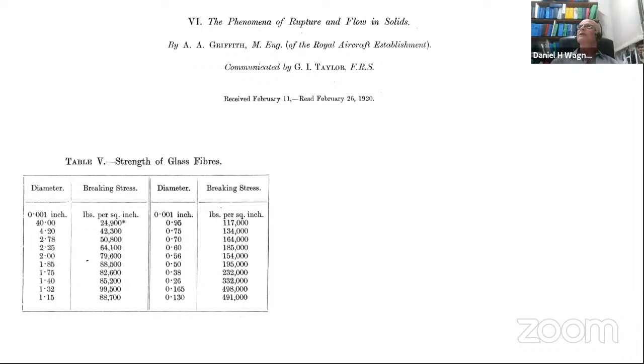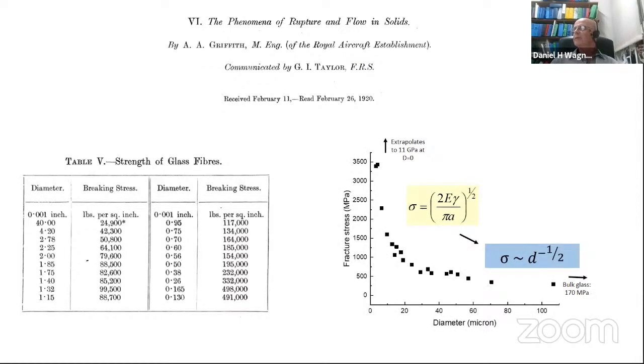And this is from the original paper of Griffith, 1920. So I took the data and I plotted them. I transformed the units to units I know better, which are micron and Pascal or megapascal. And this is what I got. The strength is proportional to the diameter, looking at diameter, not length, raised to the power minus 1/2. This is what Griffith's expression or model leads to. And so we have bulk glass at 170 megapascal or less, and the extrapolation goes up to the sky for glass.